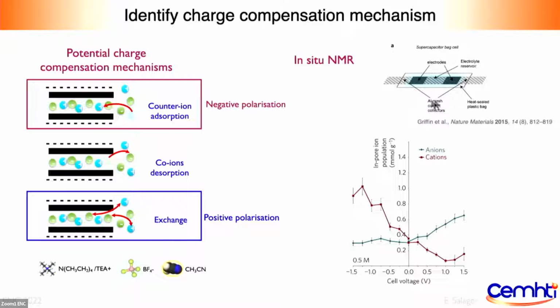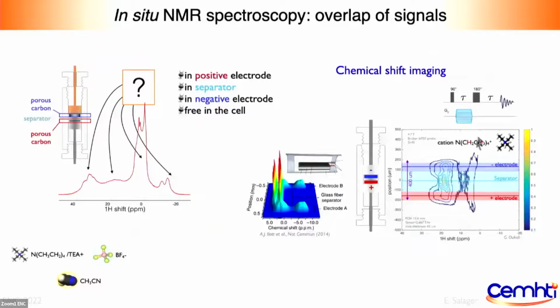So in that case, because they couldn't look at the whole device, as everything would be overlapping, what they did is that they slid apart the two electrodes so that only one was inside the coil and was measured. So that was a physical separation of the two electrodes. And so we decided to go with our electrodes to see what was going on.